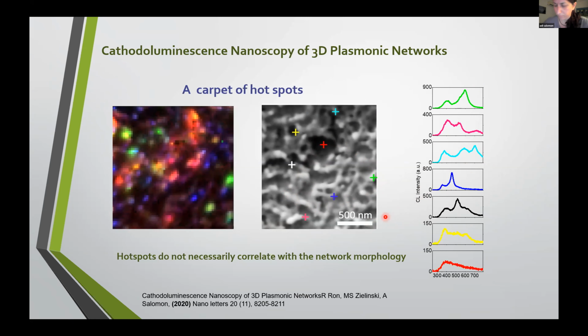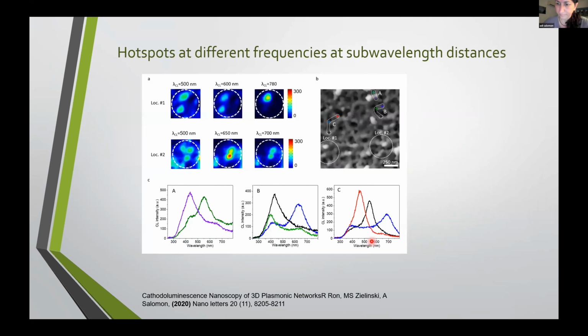We definitely see that the particles are more enhanced. We can see that we also have a nice phenomenon of hotspots at different frequencies at sub-wavelength distances, as you can see from this example. So at about 100 nanometers or 200 nanometers, you can find over the network basically all the plasmonic modes over the visible range.